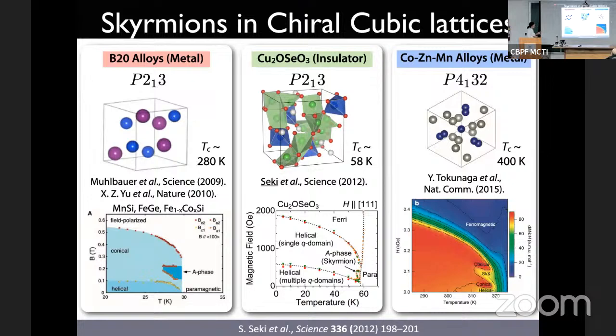So these skyrmions are seen only in a narrow pocket in the HT phase diagram. So for instance, for manganese silicide or copper oxyselenite, if you remember from the previous slide, these were some of the most well-studied materials. You find that they define a phase called the A phase here in the HT phase diagram, and this is where the skyrmions are present. So they are seen in a very narrow region in the HT phase diagram. So you're looking for this exotic spin arrangement in these narrow pockets in the HT phase diagram.